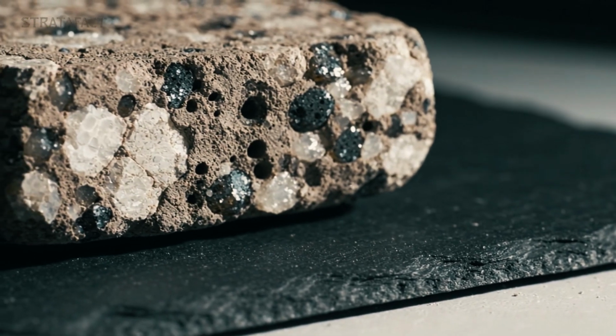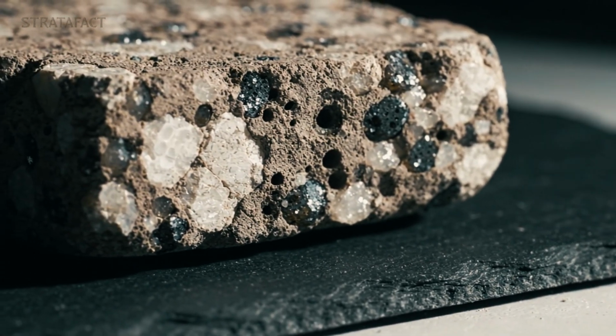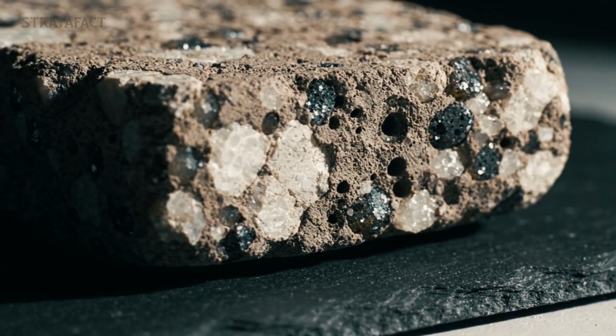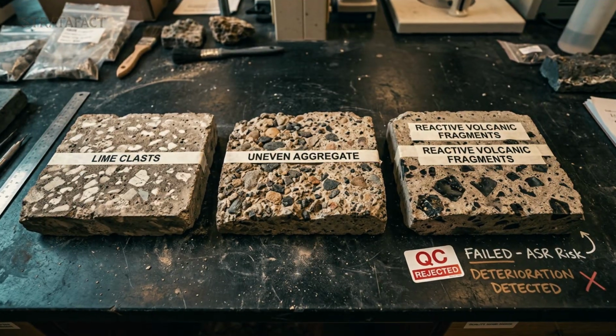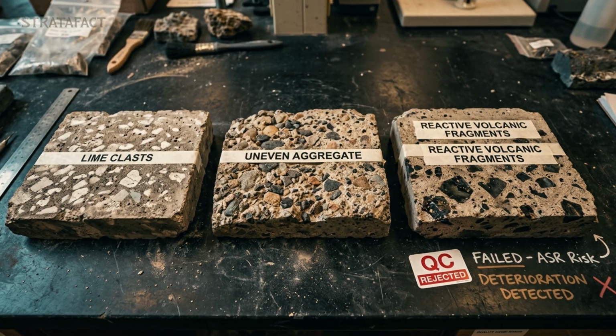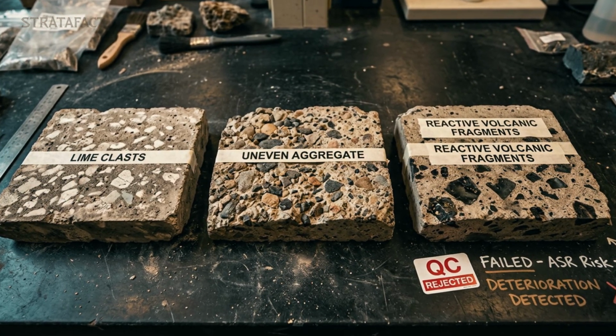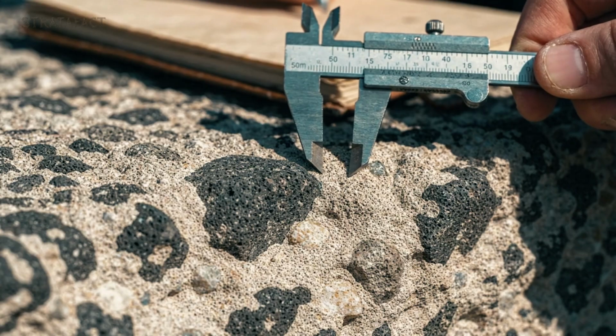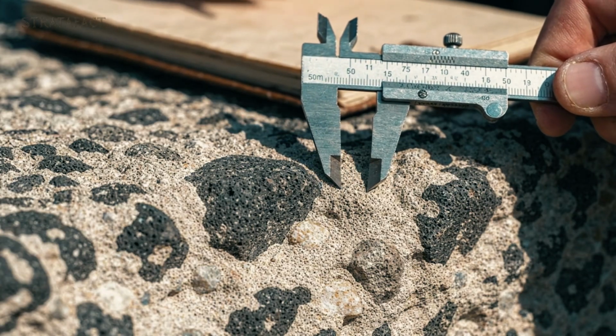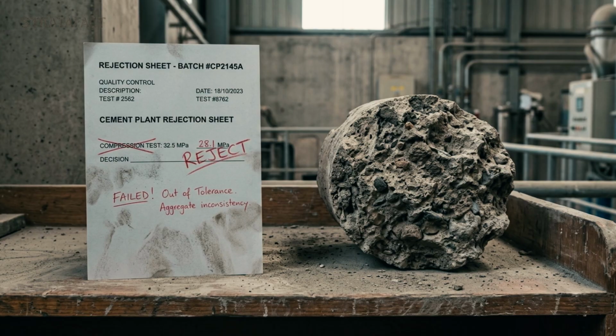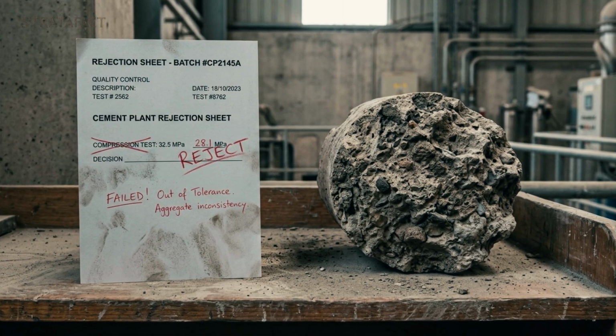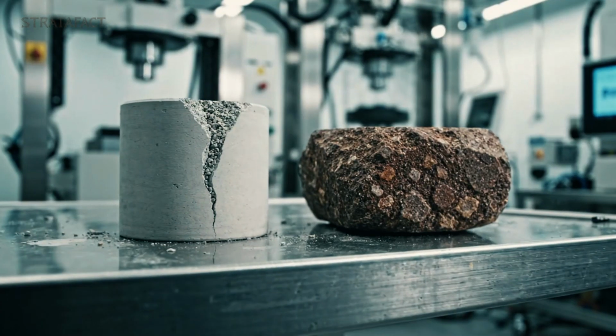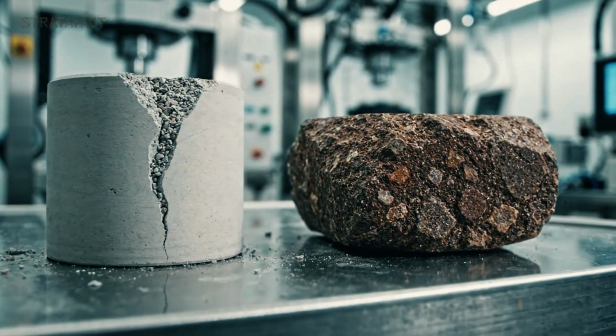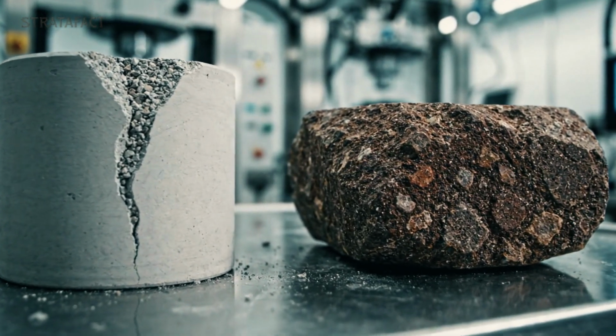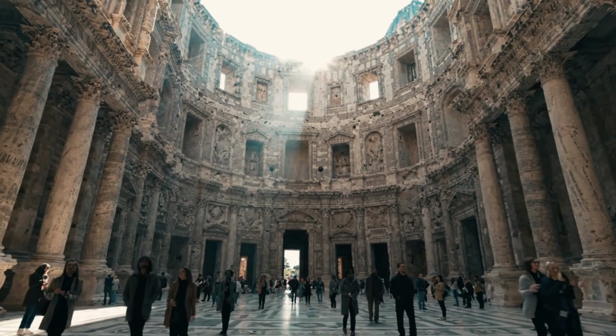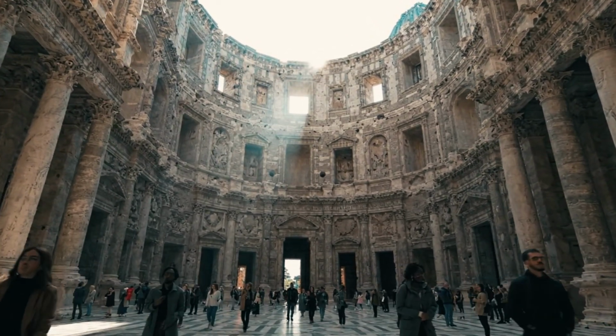Roman concrete contains features that modern quality control would treat as defects: white lime clasts, uneven mixing, reactive volcanic aggregate distributed unevenly through the matrix. The material is heterogeneous in ways that would flag for rejection in a modern cement plant. In modern concrete, those characteristics are warning signs, indicators of incomplete hydration, inconsistent performance, reduced structural reliability under load. In Roman marine concrete, they appear to be part of the reason the material keeps repairing itself.